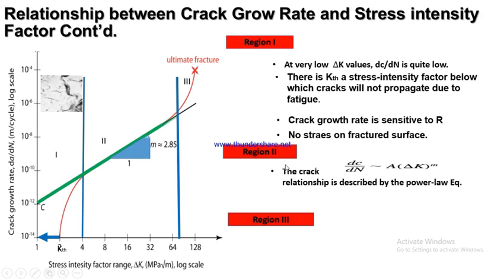Then in region 2, which is this particular place, the relationship here, which means the Paris law, becomes linear, and the crack growth depends on the power m, which you can see from here. That is why you can easily measure the slope of this particular place, because it has a linear behavior here, which depends on this power m.